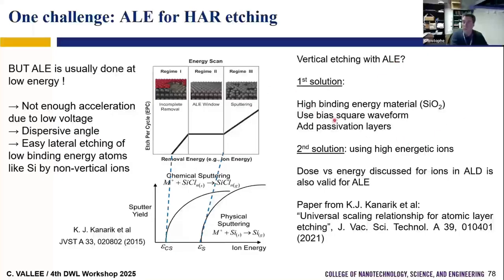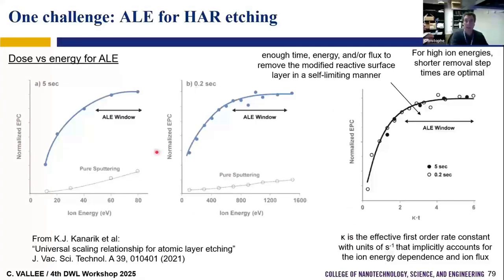One solution, for example, is to use a bias square waveform. So instead of using RF, we can use pulsed DC. And the second solution is to ask, can we, for example, use energetic ions? Can we do an ALE-like process with energetic ions? And the answer is yes, thanks to a recent paper from Kanarik, from Lam Research. Kanarik shows that what is important for the ALE window is not the ion energy, it's the dose. Because you may have the same ALE window if you use very energetic ions but reduce the ion flux, so if you reduce the time of the exposure to the ions.